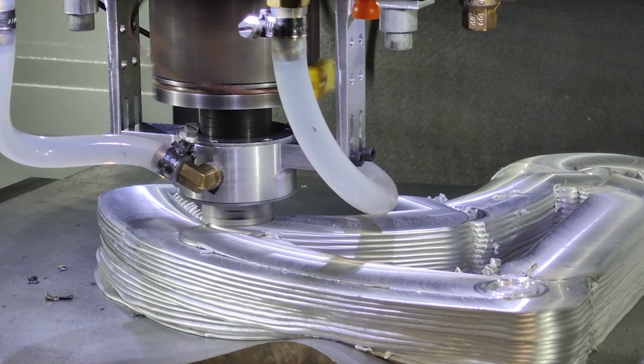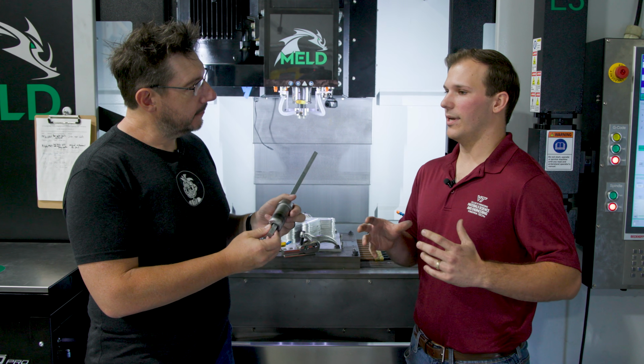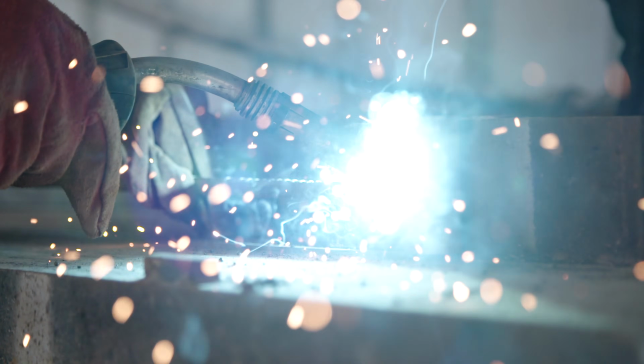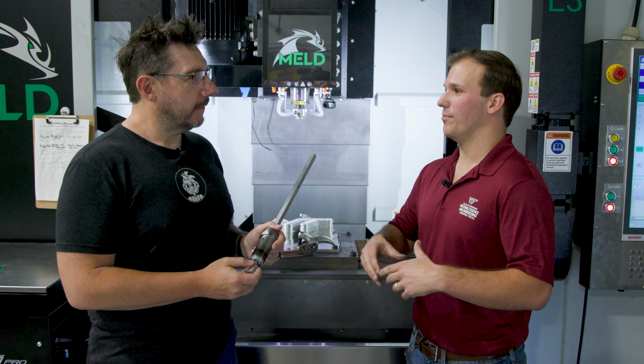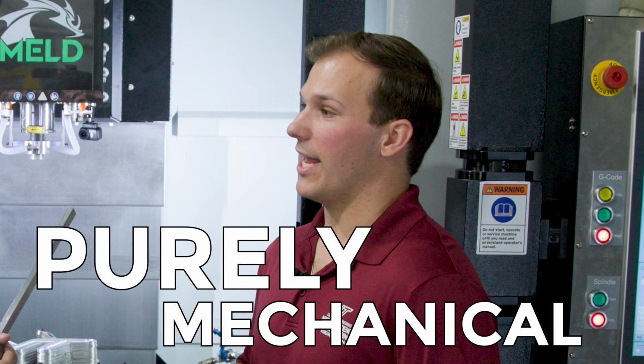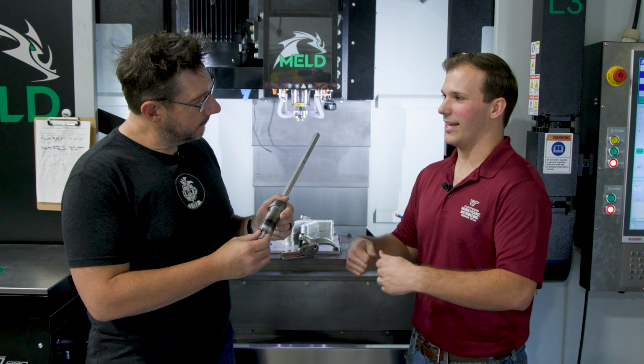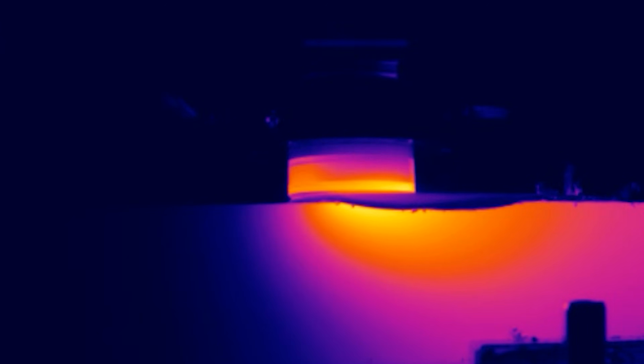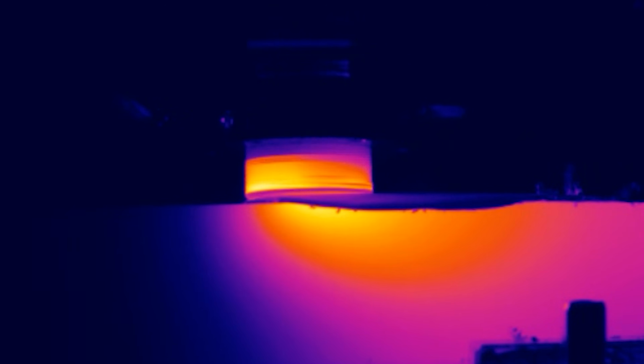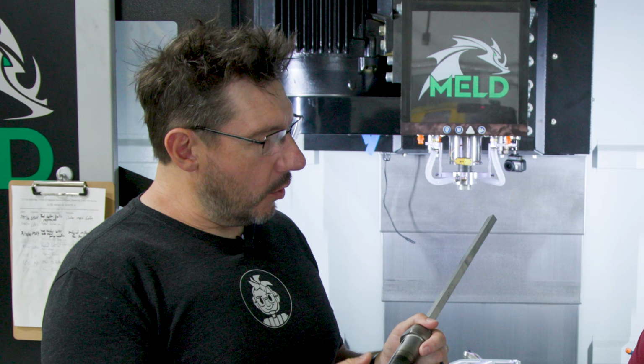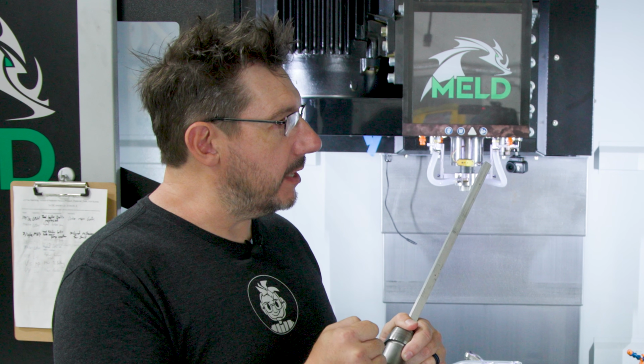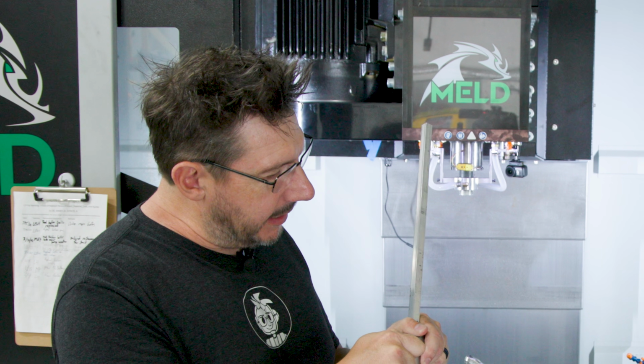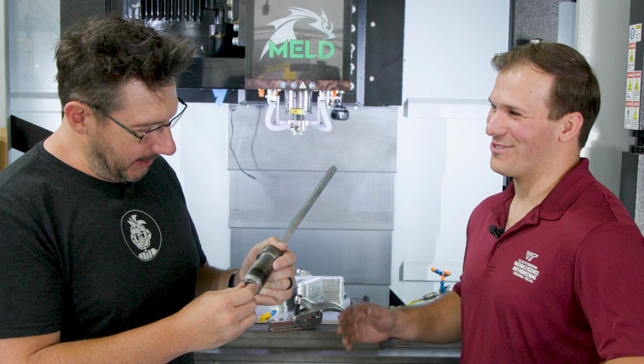And in part with the pressure and the spinning, you're getting temperature. Yes. So we don't actually input energy in the way that you would with, say, a laser process or a welding process where you're directly using electrical energy or other electromagnetic energy to melt that material or to deform that material. We're purely mechanical. So think of if you take a paper clip and you bend it back and forth, it gets hot. We're doing the same thing here. So the deformation of the material is what's actually generating the temperature and is maintaining that elevated temperature. Wait a minute. So, okay, because I've done that. I've bent a paperclip over and over, not to the point of breaking, but enough to where I can reform it, and then it kind of stays in that state. Yes. That's this? Yes, just on a much larger scale.